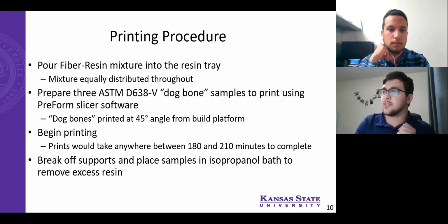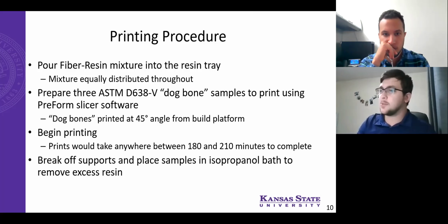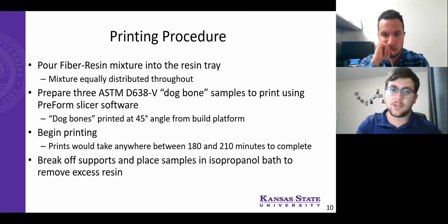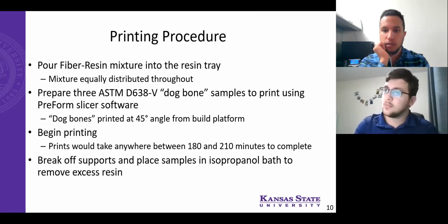And then the printing process took anywhere between 3 hours and 3.5 hours. After the printing was done, we break off the supports and place these samples in an isopropanol bath to remove the excess resin. We typically left this overnight, or in the bath overnight.